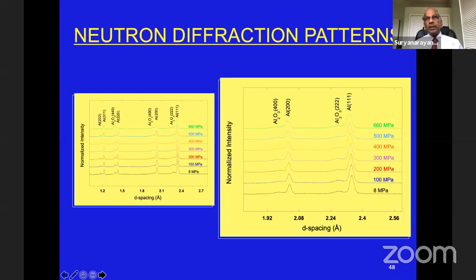But what we would like to know is, how is the load bearing capacity of this particular material? So what we did was subject this material to neutron diffraction. And when we subject it to neutron diffraction, you can record the neutron diffraction pattern. And at the same time, you can also apply a load. So if you take any one particular peak, for example, like this, and follow what the position of this peak is, that means the change in interplanar spacing as a function of stress, the change in interplanar spacing can be converted into the strain in the material, and you also know what the actual stress is.